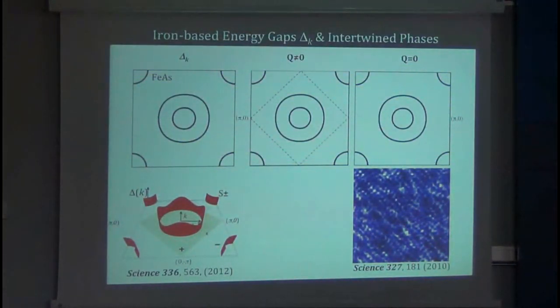Okay, so here's your homework slide for the iron pnictide superconductors. The Fermi surface is complicated. Here I show it reasonably simplified into three bands, two hole-like and one electron-like. On this Fermi surface, you have this nice anisotropic but not nodal energy gap. It seems highly likely but not yet proven that there's a change in sign of the energy gap between this sheet and that sheet. We don't find any charge density wave order parameter in the pnictides, and neither has anybody else. There's no evidence for it.